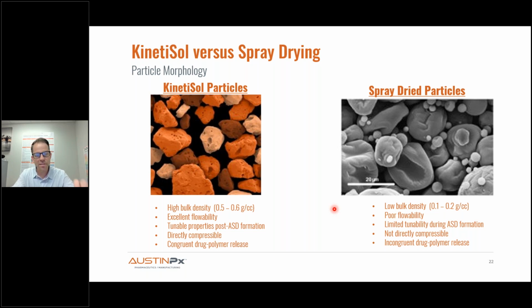As I already said, we can tune the properties downstream of ASD formation. We can use conventional milling technologies to modify the particles as we need to optimize performance of the dosage form, as well as manufacturability of tablets. Whereas, spray-dried particles have limited tunability because it's inherently part of the ASD formation process. I will talk in just a moment about the directly compressible nature of kinetisol particles, whereas, as we know, spray-dried material is not directly compressible. It has to be densified first. And then most importantly, as I will show with the case studies in just a couple of minutes, dense particles promote congruent drug polymer release. The amorphous drug substance doesn't come out of the particle until the polymer is soluble. They release simultaneously, whereas with high surface area spray-dried materials, even solvent, anti-solvent particles that have high surface area, it is very common that the drug and polymer have different dissolution rates, specifically when there are pH dependencies involved.